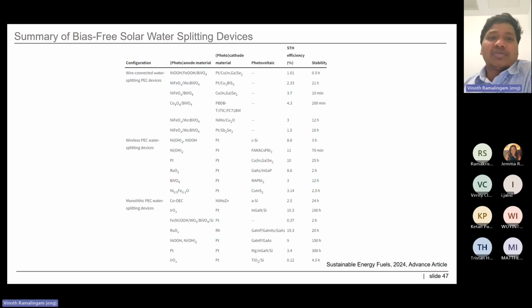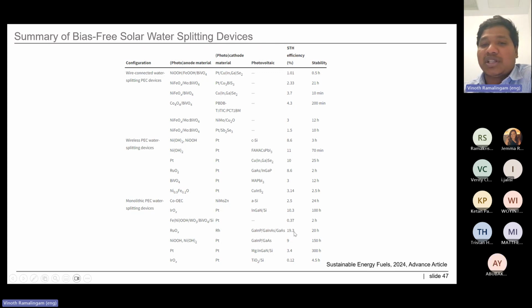So this is the summary of bias-free solar water splitting systems of different configurations: a wired configuration, where they use different photoanode and photocathode materials; this is the wireless PEC water splitting; and this is a monolithic one. So far, a maximum solar-to-hydrogen efficiency of close to 20% has been achieved, for a stability of 20 hours.